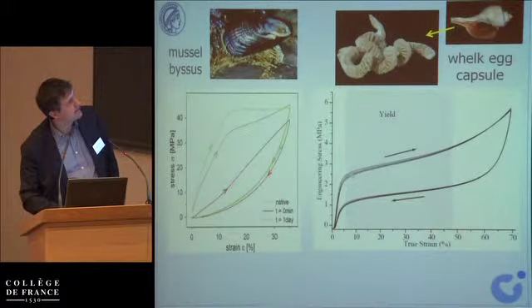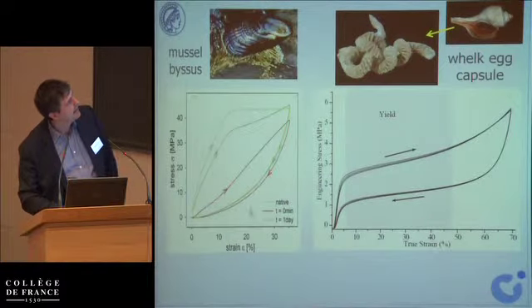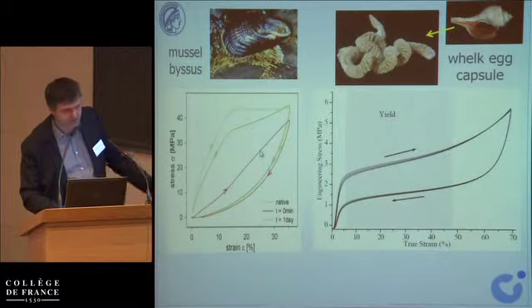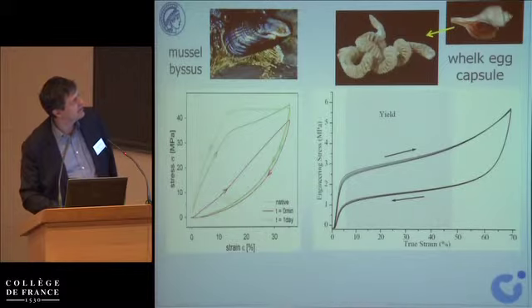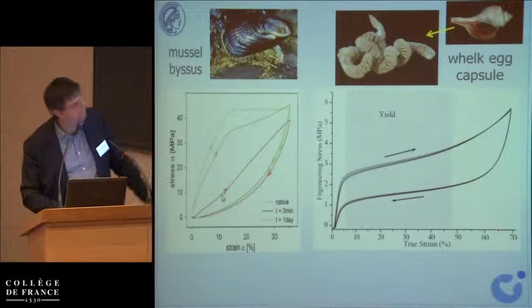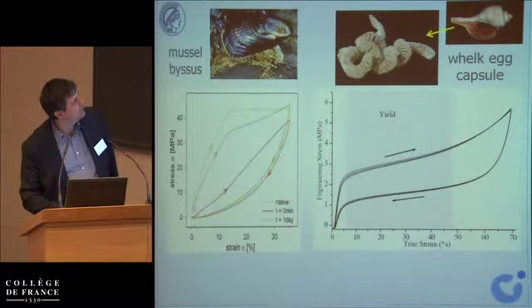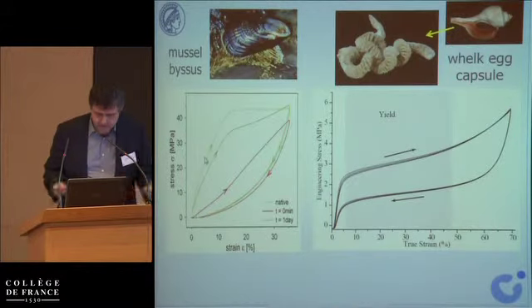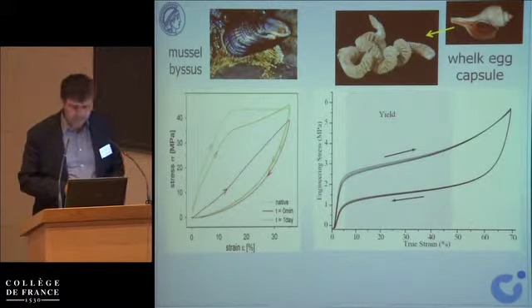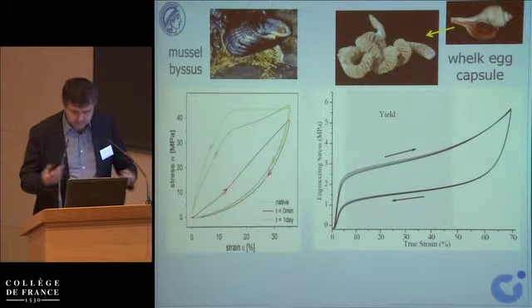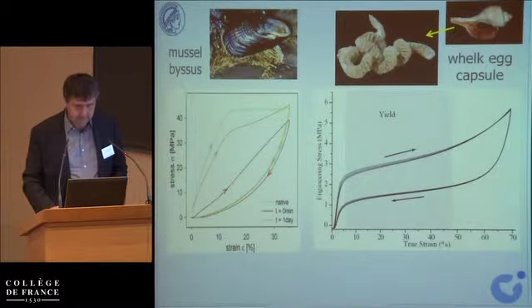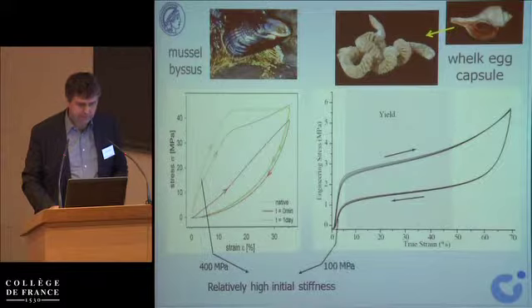It's not like here, it's not a cycle that immediately goes back. If you wait some time, a small amount of time, it goes back around this curve. So now the material has much worse properties than it had before. In particular, the stiffness in the beginning is gone. But if you wait a day, it's back to the original. So the question is, what are the designs for materials such as this? Because this, of course, is a design for durability.